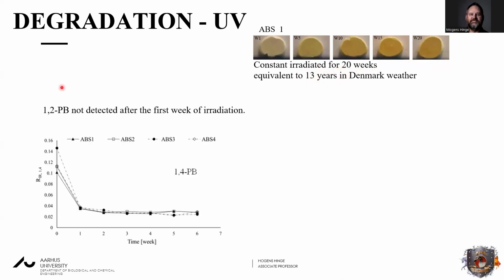years. The first thing we observed is that the 1,2-PB phase was simply not detectable after a week. So after we have irradiated this constantly for a week, then this is completely removed. We cannot see, there is no peak, it's gone. And if we look at the ratio between the styrene peak that I told before, around 700 reciprocal centimeters, and then the peak for the 1,4 butadiene, what we see is a dramatic reduction already within the first week. And then we see a slow reduction. And then after like 3 weeks of constant exposure, we start to see that there's not really anything. So that basically means that when we irradiate it, it degrades extremely fast.